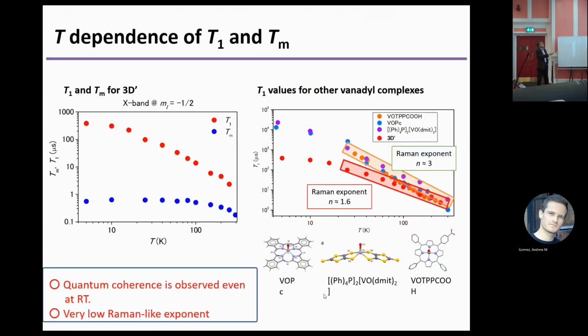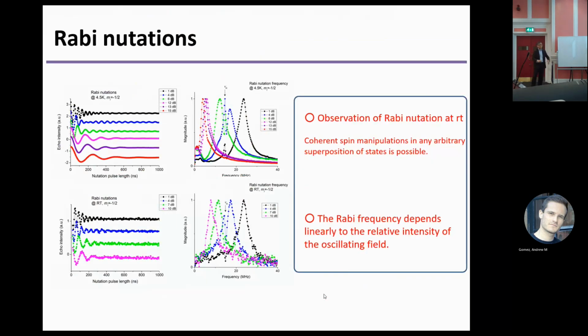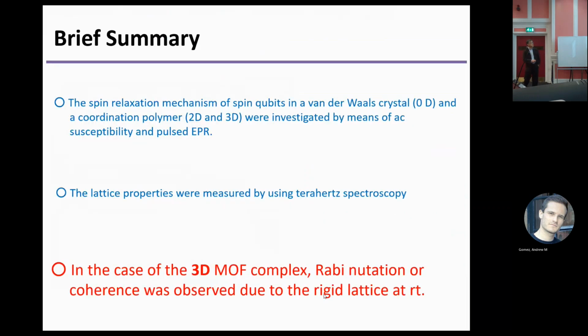So then this result: relaxation time. In the three-dimensional MOF, we observe the coherence even at room temperature. And also Rabi nutation. We apply the pulse pair and detect the echo. Usually Rabi nutation is observed at very low temperature, liquid nitrogen or liquid helium temperature. But in our case, even at room temperature, we observe very beautiful Rabi nutation due to the strong lattice. So in the case of the 3D MOF complex, Rabi nutation or coherence was observed due to the rigid lattice. So the lattice is very important.